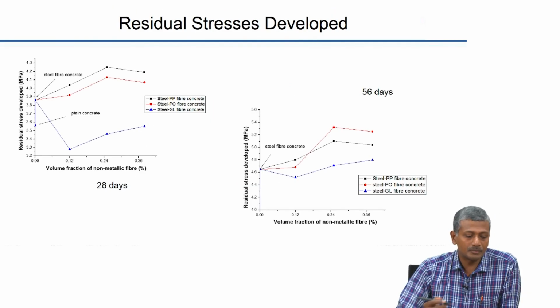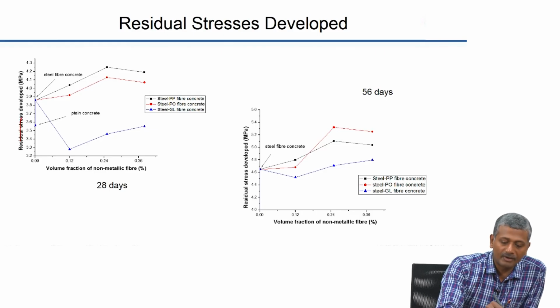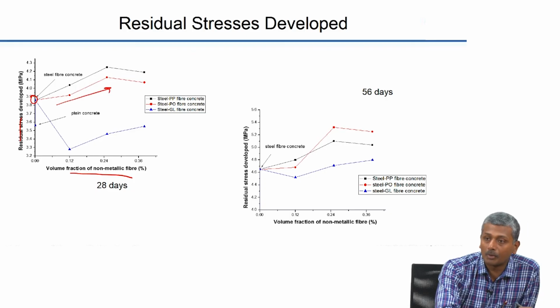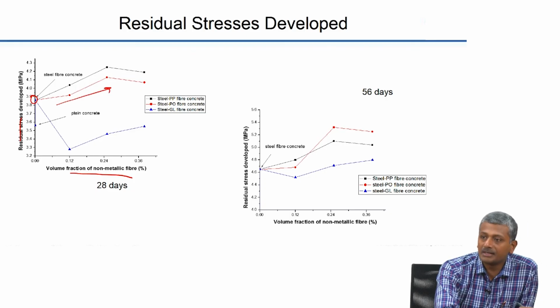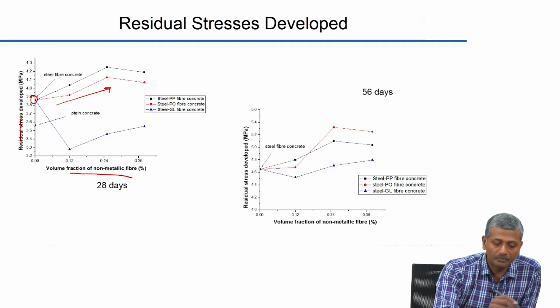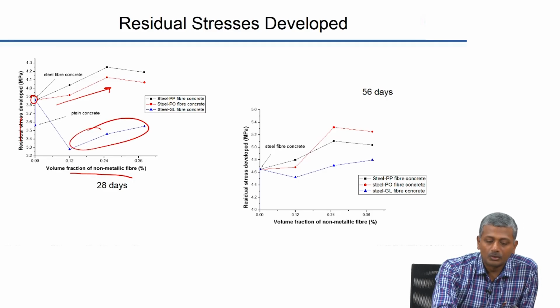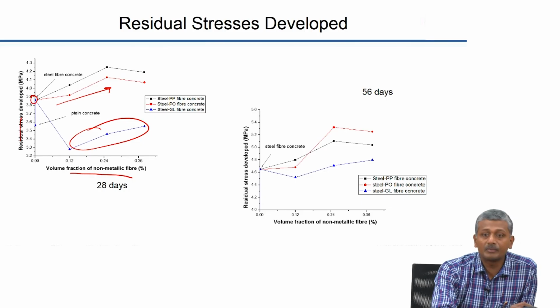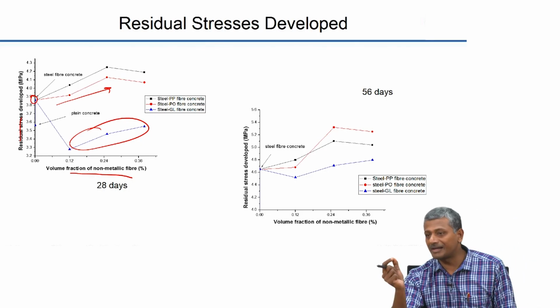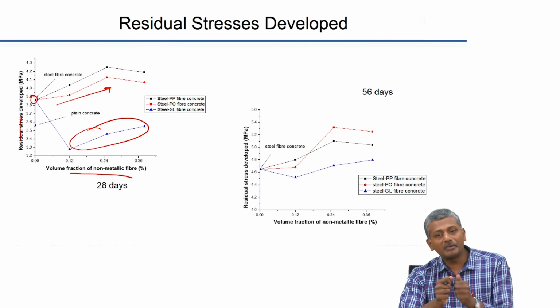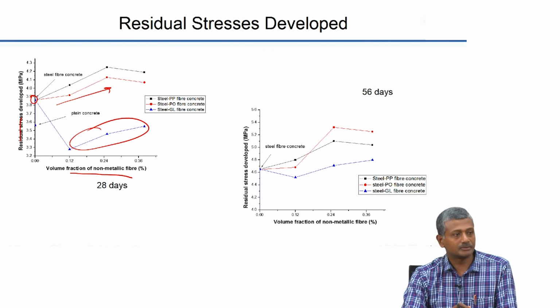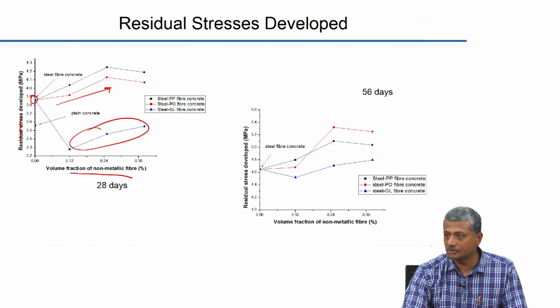So, in terms of residual stress developed as a volume fraction of non-metallic fibers, you can see that for steel fiber, we are here; as we increase the extent of polyester or polypropylene fibers, we are seeing an increase in the residual stress developed. With glass fiber, you do not see as good a performance as with steel fiber concrete. So, glass fibers, possibly because they are extremely thin, maybe even breaking as the crack appears. So, because of that, the capacity is actually going down.